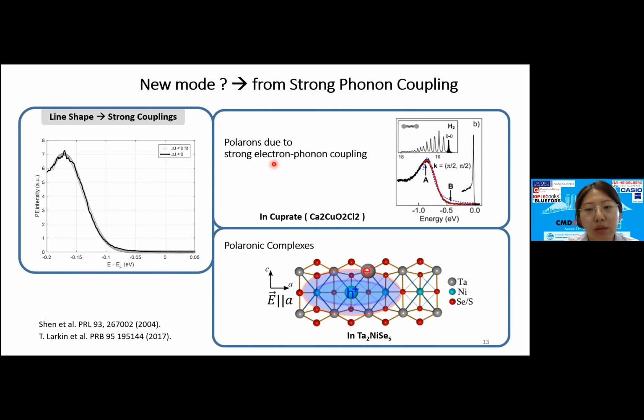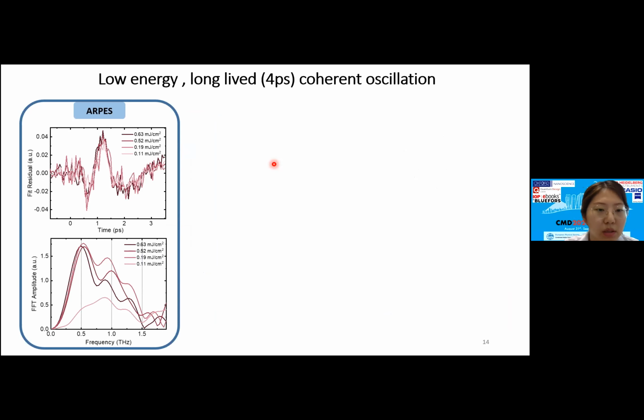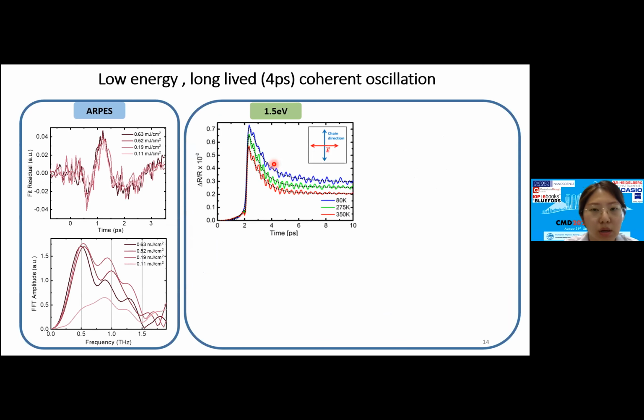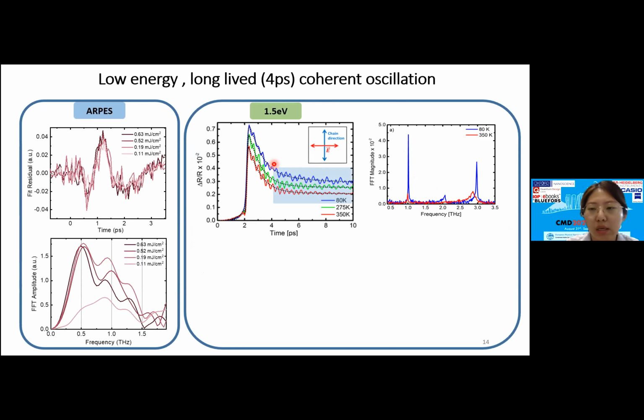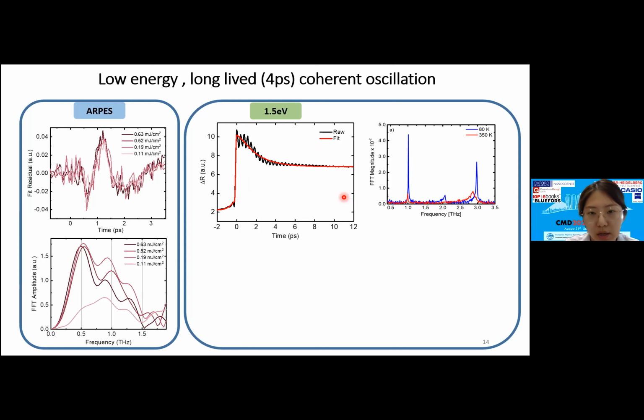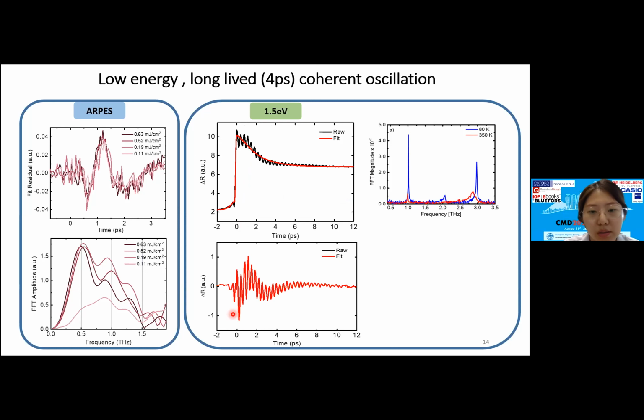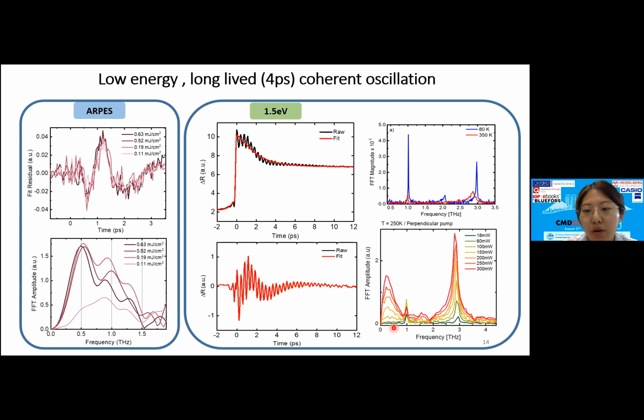So can you see this polaronic mode not only in the ARPES gap dynamics, but also in optical pump-probe dynamics? When we see the coherent phonon modes, they are cleaned out with only a longer time delay. But at the whole time delay, we found there is an oscillatory behavior at the early time. With an FFT of this total dynamics, we could find this polaronic mode at a similar energy range as we saw in the ARPES measurement.